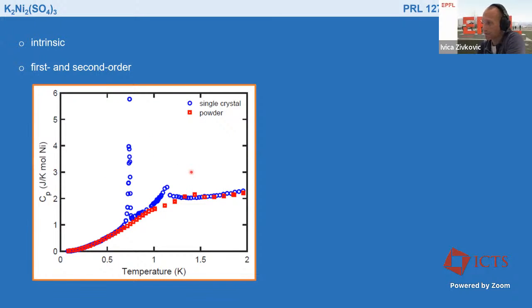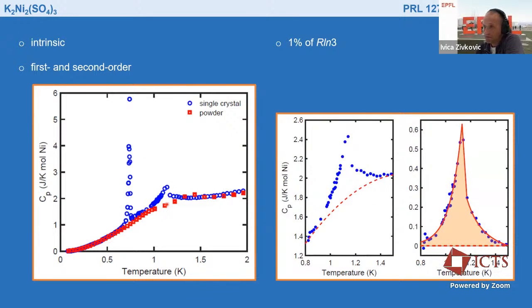And as I will explain a little bit later, this corresponds to something that we believe is a realization of a weak order, a second order phase transition into an incommensurate structure, and then later there is a first order phase transition into a commensurate structure. If you look at this peak, which we believe is of second order type, and look into the total entropy released across this transition, you end up with only 1%. So a very, very small amount of freezing actually occurs at that transition.